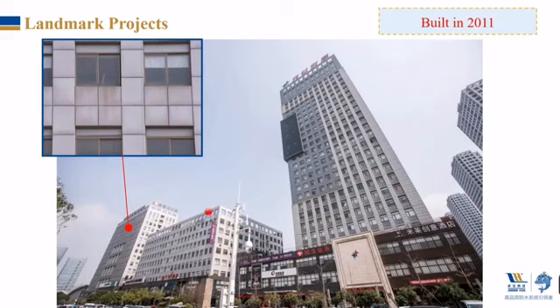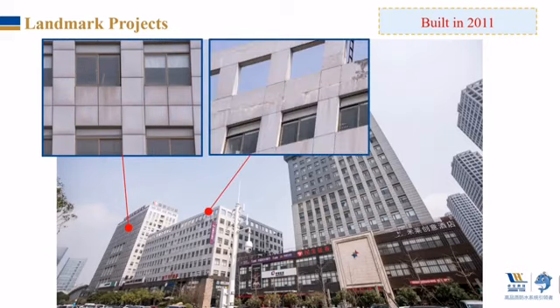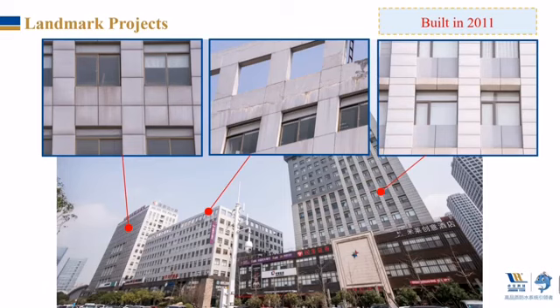For the building in the middle, which uses coating plastering system, there are signs of cracking, falling off, or seepage on the surface. For the building on the very right side, which uses our aluminum integration system, it is still very flat and complete on the surface, with only a small amount of gray dirt that can be washed away. So that's an excellent example to show the durability of our system.